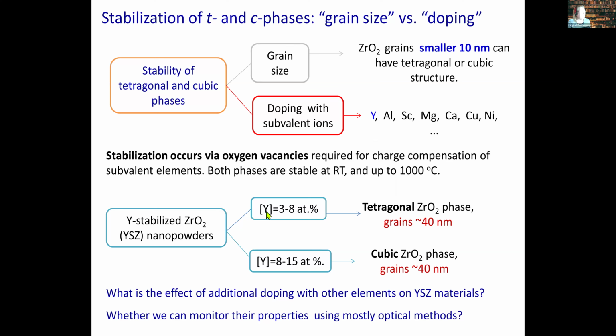As known from history, it's possible to stabilize tetragonal and cubic phases via two effects. One of them is grain size. Due to the high ratio between surface area and volume of the grain, surface tension can achieve stabilization of tetragonal or cubic phases. In this case, the grain sizes of zirconium oxide can be about 10 nanometers. And if we do not anneal at very high temperatures, like 1,000 degrees Celsius, the stabilization will be perfect. The other way is to dope with subvalent ions.